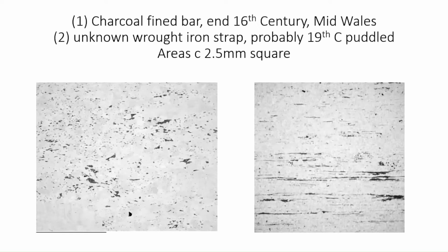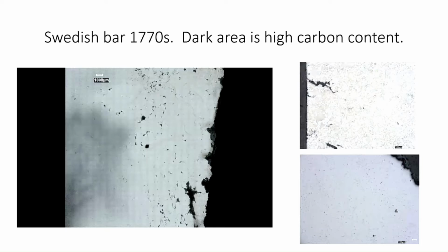But it wasn't just slag that gave you this heterogeneity in bar iron, because you got a terrific variation in the carbon content. And this is a section, it's actually a composite map of a bar iron that was found off the coast of Holland. And you can see that dark area on the left. That is high carbon. In fact, the top picture is from that dark area and shows that that's almost entirely pearlite, which has got a carbon content under normal circumstances of 0.8, but I suspect that given the presence of other impurities, that's probably a bit less than that. Whereas the light side has got virtually no carbon in it at all. It's all ferrite.